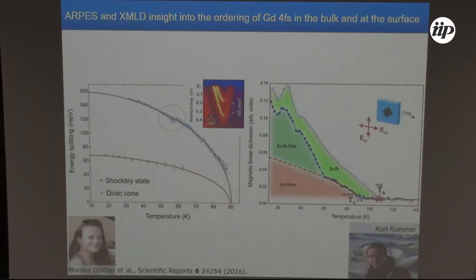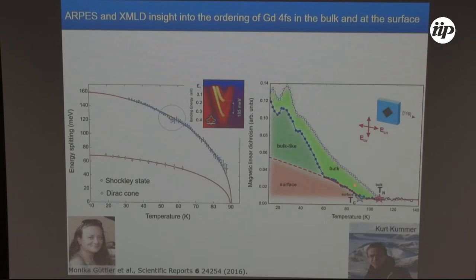This was also interesting — why should they differ? In the next experiments performed at ESRF using XMLD measurements with a fluorescence yield detector and a total electron yield detector, we measured the gadolinium M4,5 edges to see what happens at the surface and in the bulk. The fluorescence yield suggests that bulk magnetic order onset is already at 107 K, while the electron yield suggests that magnetic order at the surface happens at much lower temperature, around 90 K. Moreover, both curves behave differently, but something happens around 60 K where a strong kink is seen, and after that both curves demonstrate similar behavior.